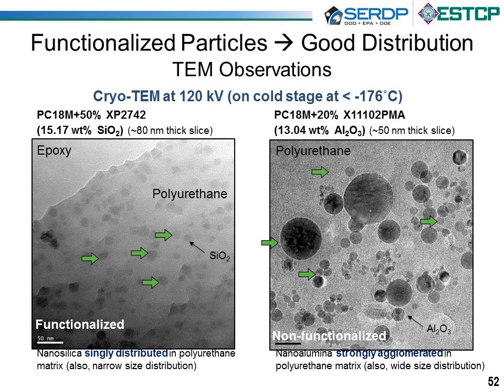But all in all, regardless of the filler, if you look at the size of the filler and the amount of fill we had compared with the whisker diameter, the whisker is about 20 times the scale bar. It's about 1 micron in diameter. The scale bar down here is 50 nanometers. So we've got a lot of particles available to provide isolation if a whisker does start working its way through the polyurethane resin. These particles are really going to provide good blocking for us.